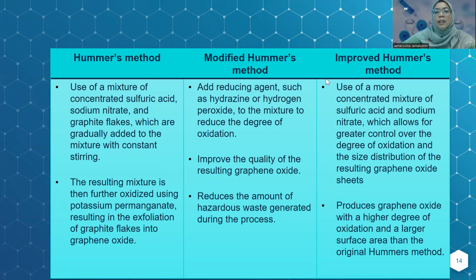Last one in the Hummers methods, we have the improved Hummers method. The improved Hummers method uses a more concentrated mixture of sulfuric acid and sodium nitrate, which allows greater control over the degree of oxidation and the size distribution of the resulting graphene oxide sheets. And also, the improved Hummers method can produce graphene oxide with a high degree of oxidation and a larger surface area than the original Hummers method. So from these three methods, the improved Hummers method is the best.